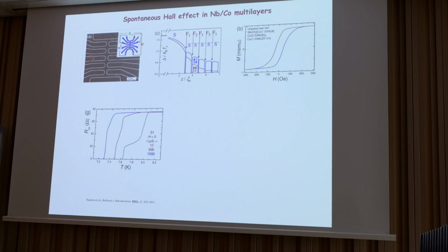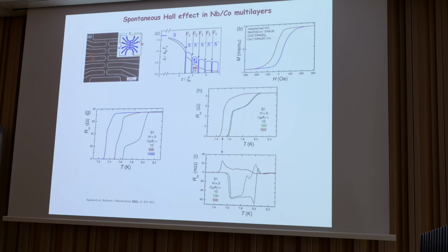This is simply because this point corresponds to the case where the depairing current becomes smaller than the transport current, and then the resistance falls down to zero when the critical current becomes smaller than the applied current. And we can continuously tune it. So there is no suppression of superconductivity whatsoever here. It's just a transport effect.